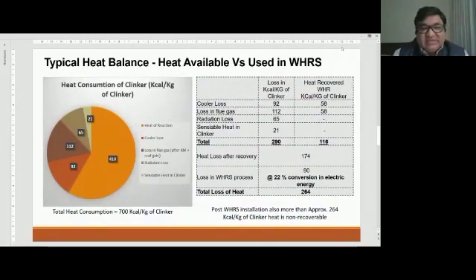Just to give you an idea of how much energy is available from the plants and how this energy can be used. If you take the example of a typical operating plant, normally we say about 700 kilocalories per kg of clinker is consumed to produce the clinker. Out of that, 410 is needed because your raw material needs to be burned to clinker, which is called heat of reaction. But the remaining heat goes to different areas, especially losses, radiation, and some goes to the material which goes out from the process. It means only 410 of the 700 kilocalories of heat is really utilized to produce the clinker in our clinker process.